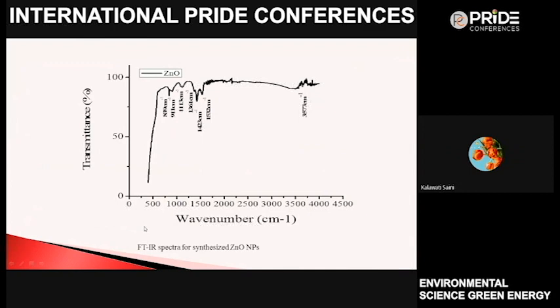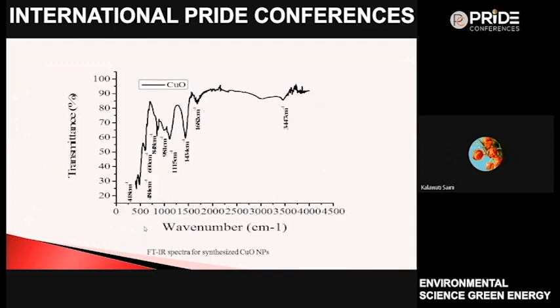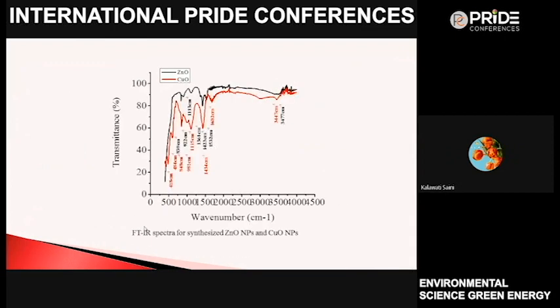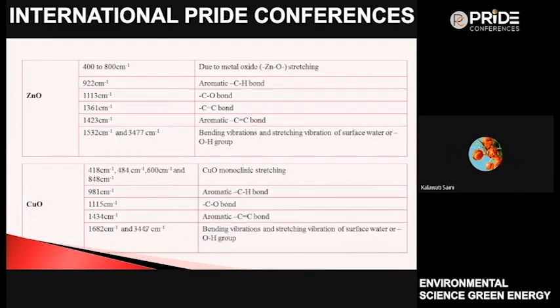These are the FTIR spectra, which show the presence of phytochemicals in the zinc oxide as well as in the copper oxide nanoparticles. This is the comparative FTIR spectra. These are the characteristic transmittance bands regarding both green synthesized zinc as well as copper oxide nanoparticles. These are the specific groups which are present in their coating.